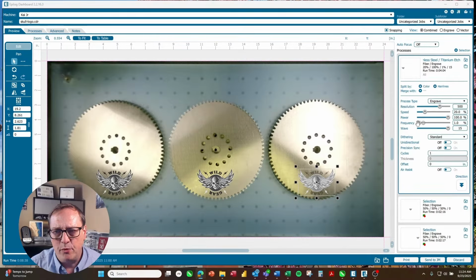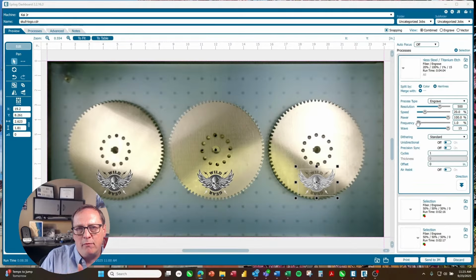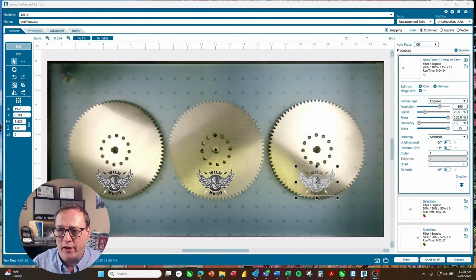Now for frequency, we've got that all the way down to 1%. When we're saying low frequency, that is the number of pulses happening per second. There are fewer pulses, but more energy per pulse, so that more energy can blast away, or ablate, more material each time the laser fires. Now for waveform, we've got this all the way up to 15. The reason is it's a long pulse duration, so it pulses longer, you have more heat applied to the material, and you can remove more material. So I'll go ahead and do this one bottom up engraving, and we're all set for our etch mark.